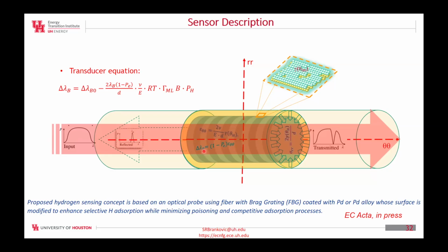Therefore, the shift is very sensitive to the strain in the grating. And if we coat the fiber with a particular material, for example, a catalyst that is very active to hydrogen adsorption, then the Laplace pressure, because those are small diameter fibers, will be a function of the surface energy of the fiber coating, which is our catalyst material, and indirectly this surface energy will be modified by the adsorption process, which is going to be again a function of the pressure of the hydrogen. And change in the pressure of the hydrogen will be reflected basically in the shift of the Bragg wavelength. And that's how you can actually measure tiny amounts of hydrogen or small pressure changes of hydrogen